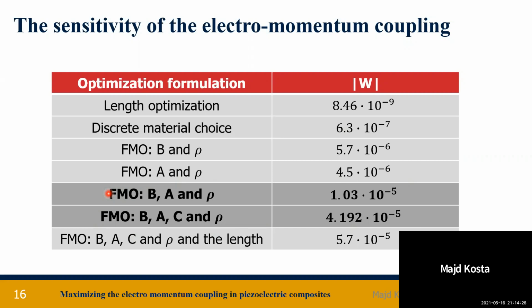And we also note that we tried to do the same process for any couple that includes C, the material stiffness, but that didn't lead anywhere, which means that breaking the symmetry of the stiffness, or optimizing the electromomentum coupling over C, the material stiffness, is not enough to produce the electromomentum coupling.